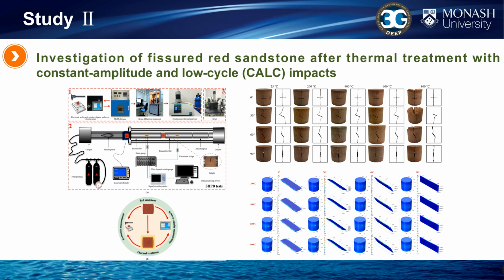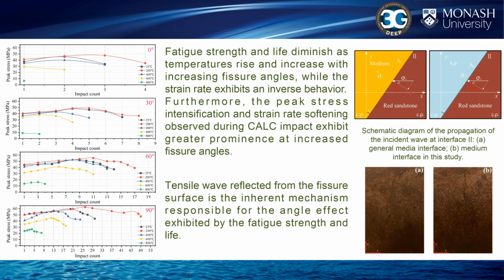The effects of crack angle and temperature on the dynamic and fracture behavior of the CALC treated specimens were analyzed, with discussions focusing on some properties, stress development, damage, stress wave transfer behavior, and structural features. As shown in the left image, the fatigue strength and life diminish as temperatures rise and increase with increasing fissure angles, while the strain rate exhibits an inverse behavior.